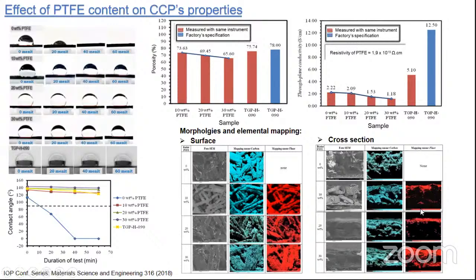And we also observe the variation of PTFE content on our CCP properties. We use three different PTFE contents: 10%, 20%, and 30%. And if we check the properties, we can see that 10% PTFE is the optimum content that produces good properties in our CCP. This is the porosity. We know that PTFE can block the porosity of our composite, but with 10% PTFE, the porosity is still high, and it's good, I think, compared to the commercial carbon paper.